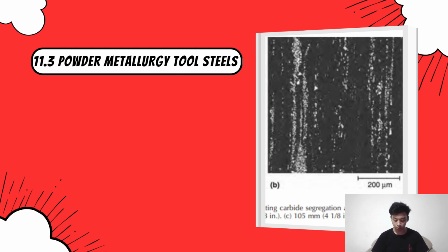Powder metallurgy tool steel. As a result of pronounced ingot segregation, conventional tool steels and high-speed steels can contain a somewhat coarse, non-uniform microstructure accompanied by relatively low transverse toughness properties. The carbide segregation observed in the longitudinal section of annealed M2 high-speed steel bars, as in picture 11.8, illustrates the degree of segregation that is normally present in these bars and how it becomes more pronounced as the diameter of the bar increases.